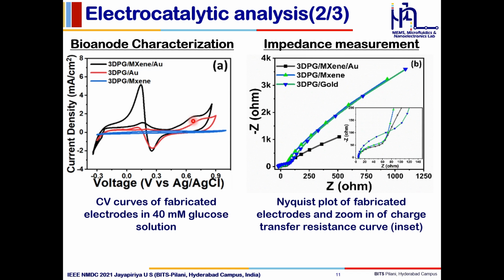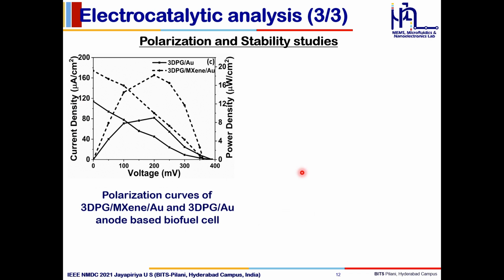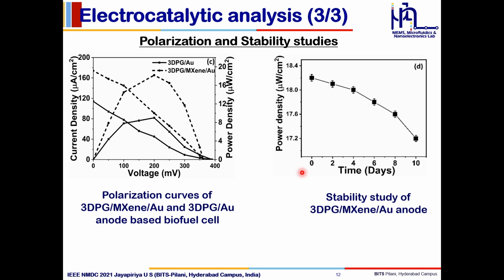Similarly, to understand the interface effect of MXene and Au on the 3D printed electrode, electrochemical impedance spectroscopy was done. It can be clearly seen that in the presence of MXene and gold nanoparticles on the 3D printed electrode, it has a lesser linear area and charge transfer resistance. Thus, these electrodes prove to be a good anode for a non-enzymatic biofuel cell. Hence, to confirm this, we did the polarization studies, and the plots were done with the help of chronoamperometry. It can be seen that in the presence of the MXene Au coated 3D printed electrode, the biofuel cell was capable of producing a high power of 18 microwatts per centimeter square. Also, the electrodes were able to give around 90% of their initial power performance until 10 days.